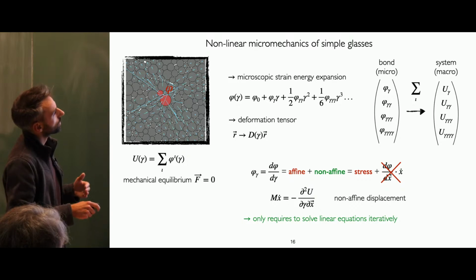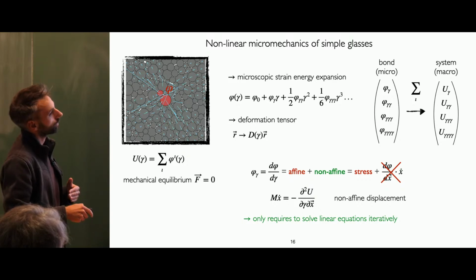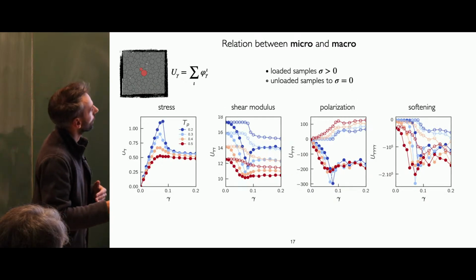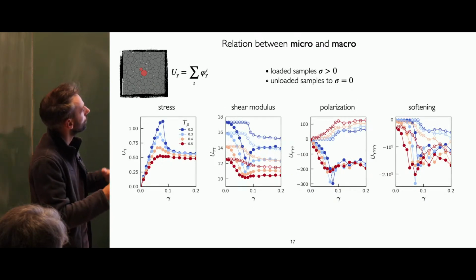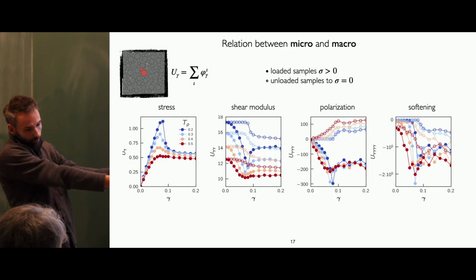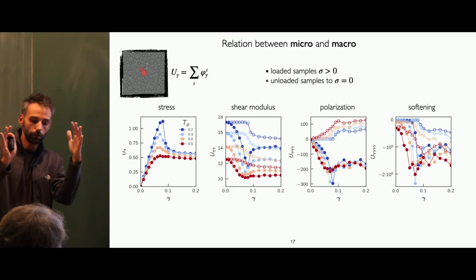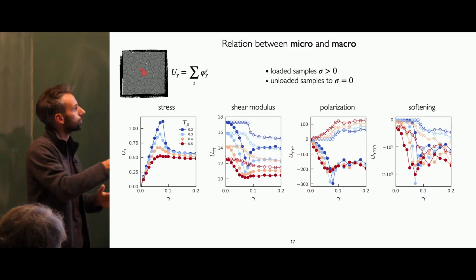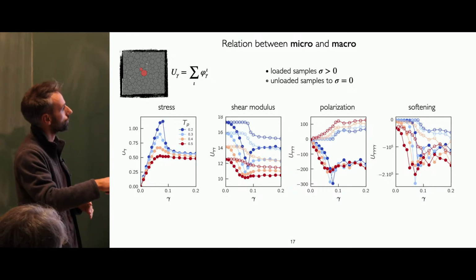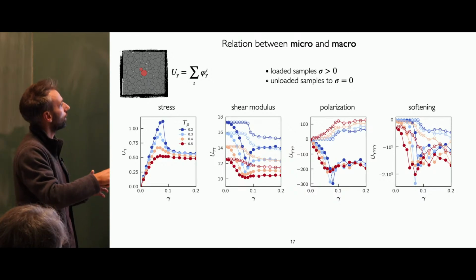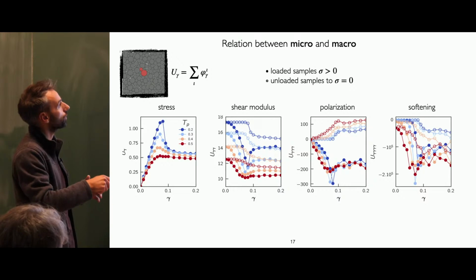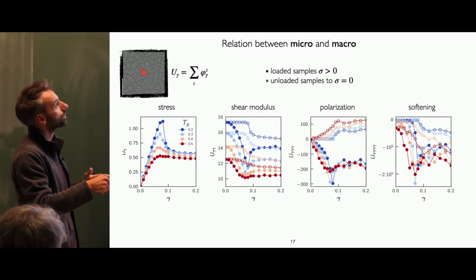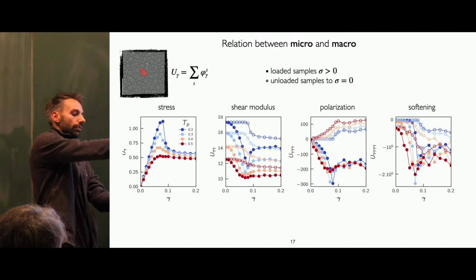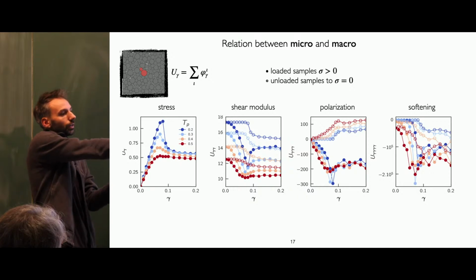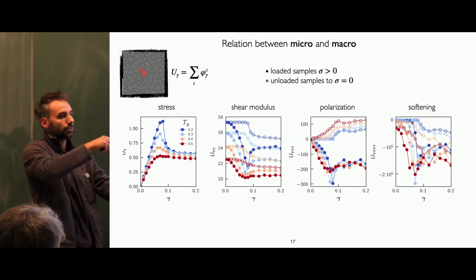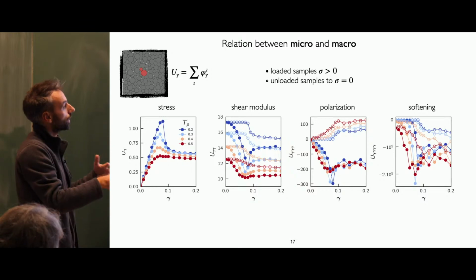So maybe just one slide on the relation between micro and macro. With this framework, without looking at the microscopic, you can already get the macroscopic nonlinear coefficients of a strain energy expansion. So you can follow all these coefficients as a function of strain, for different preparation protocols, and you can look at loaded samples. So I shear and I have a state at finite stress, and I can also unload my system, for example at 0 stress, and look at the evolution of that.